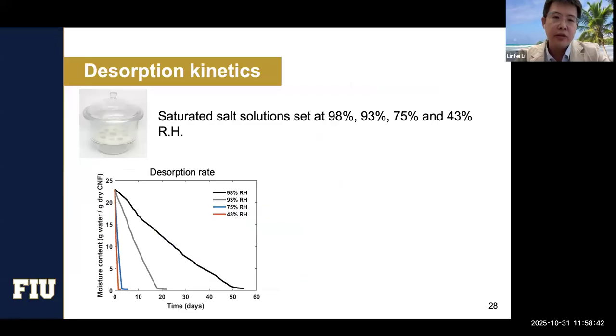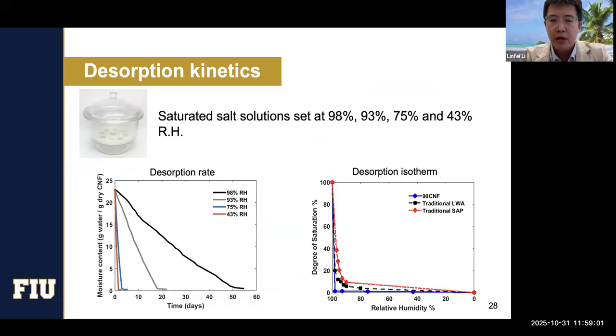Following that is the desorption kinetics. We know how much water the CNFs can hold, but we also want to know how the CNFs release water at different relative humidity. So we use a saturated salt solution to create different relative humidity. You can see the desorption rate here for different relative humidity, and on the right-hand side is the desorption isotherm.